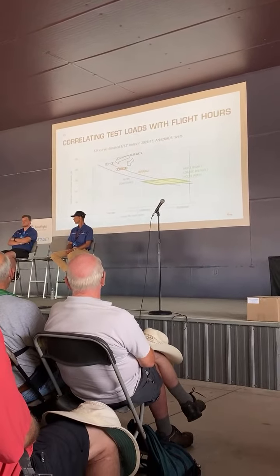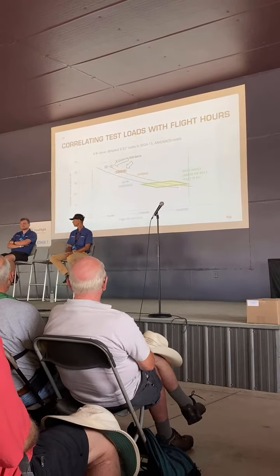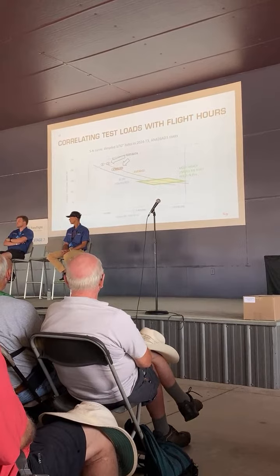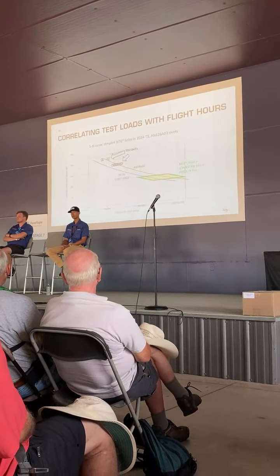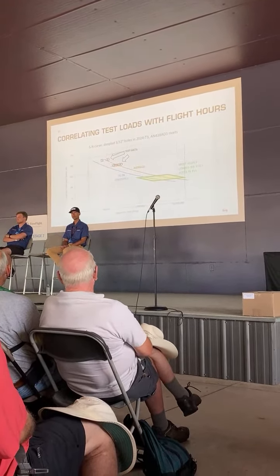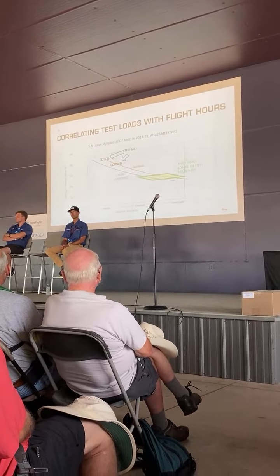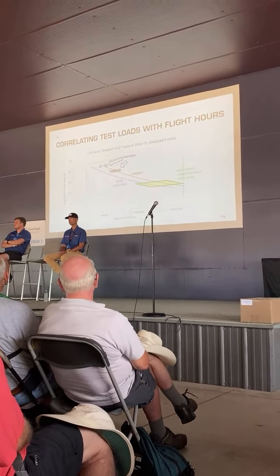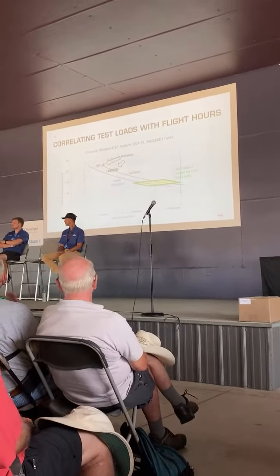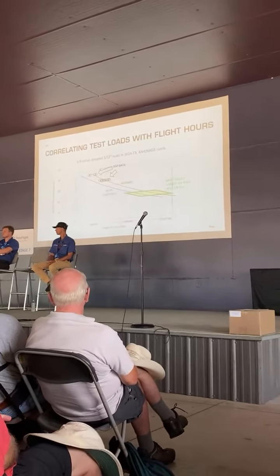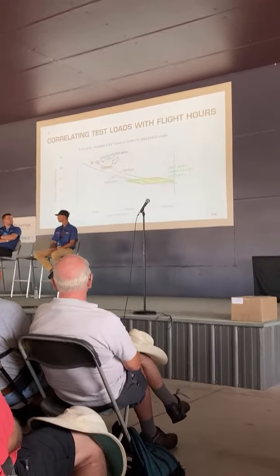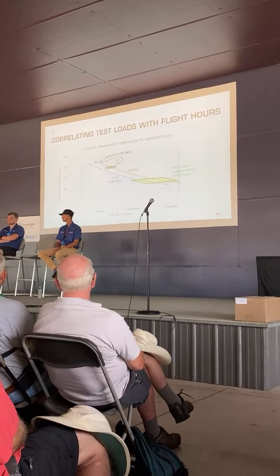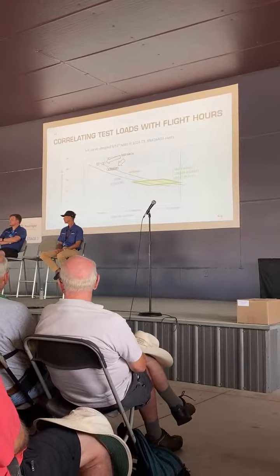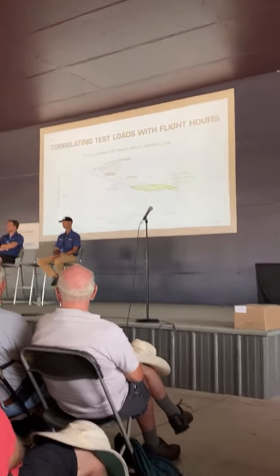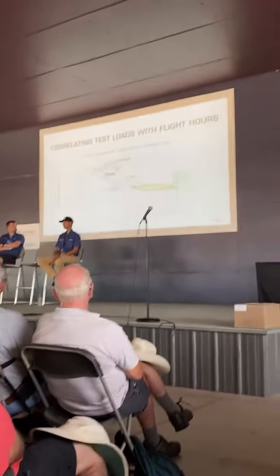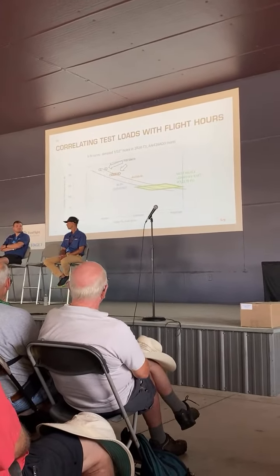From that, mathematically, we draw a line down to the left on this curve that says that you only have a 0.1% chance that any future event would occur over this line. So that's just your safety zone. And that's what you use to determine your fatigue life. You can see here that here's the stress level. Those rivets that I was talking about, they're either the front and the back of a main rib or the back two rivets on a D cell. Those are the highly loaded rivets, or the most highly loaded rivets, and they fall in this band.